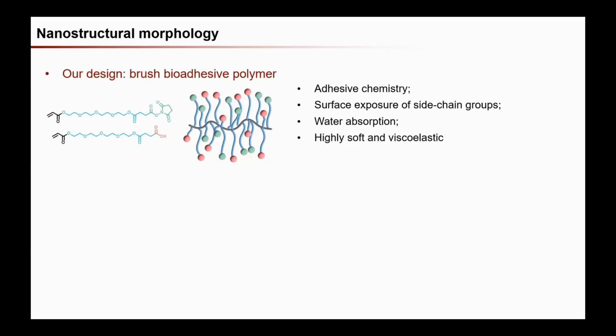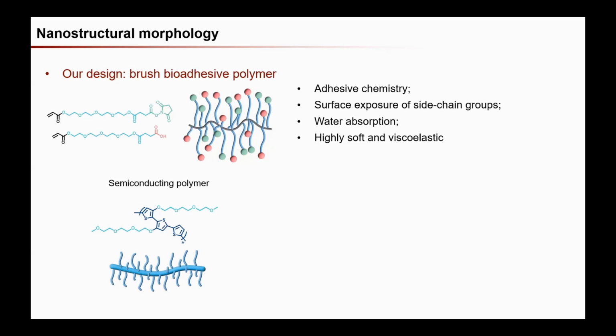First, at the end of the side chain, it needs to have a functional group that can form covalent and non-covalent interactions with the tissue, like with a protein or peptide on the tissue surface. This is what really gives the adhesion property. And then for grafting these groups onto the side chain, another key is to introduce a long extender of the side chain to make it into a brush. The reason is that this has to be blended with this kind of semiconducting polymer, which usually has a very long side chain for processability and also ion conducting property.